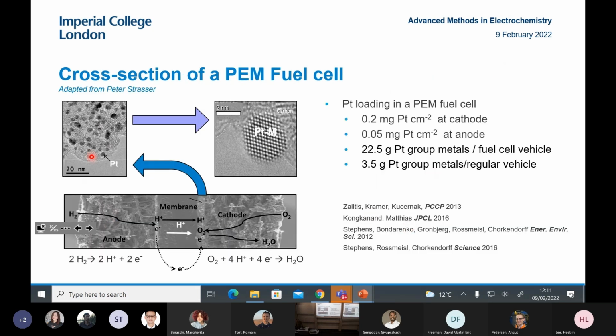Obviously, when you look at an actual fuel cell, it's quite complex. It's quite difficult to actually do measurements on a real fuel cell because it's difficult to optimize, especially in an academic lab. And what I'd like to point out is that you need a lot more platinum catalyst to drive oxygen reduction than you need for hydrogen oxidation. That's because oxygen reduction is intrinsically more difficult to catalyze. I'll be explaining why in a moment.